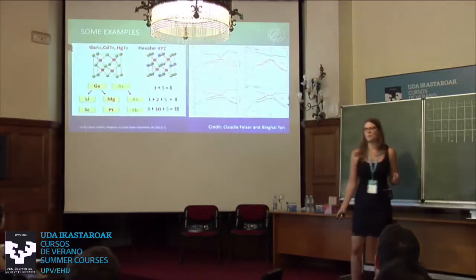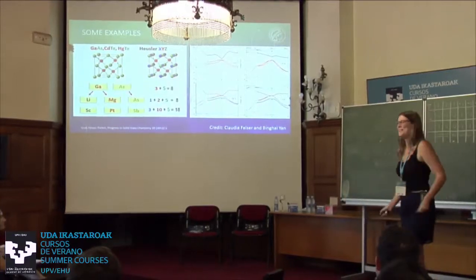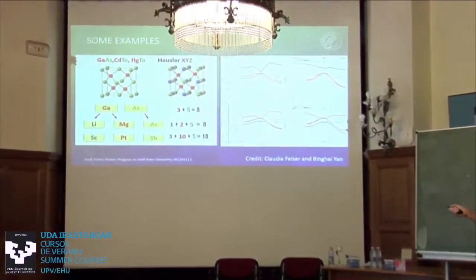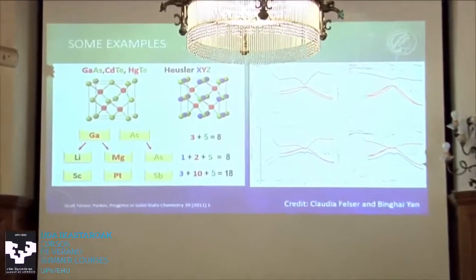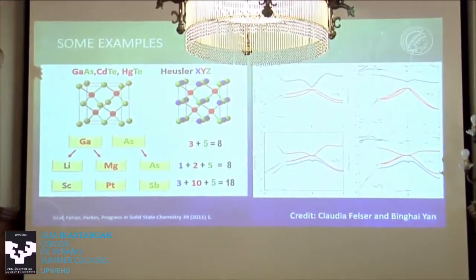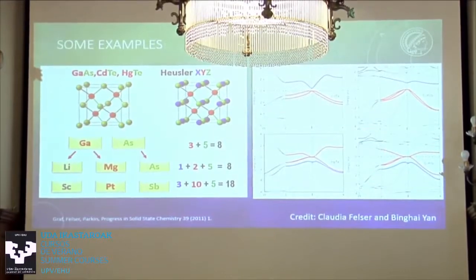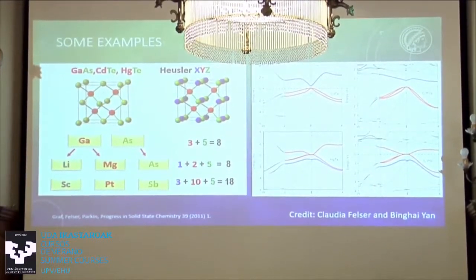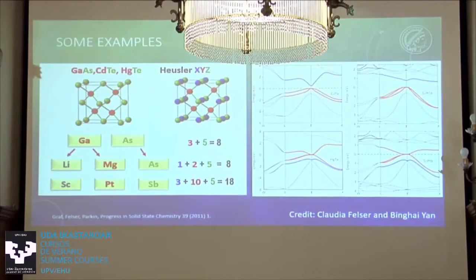This is a slide I stole from Claudia. I hope she's not going to tell you the same thing later. If you have a semiconducting compound, you all might know gallium arsenide, you have 3 and 5 electrons, it's 8, so you have a semiconductor. But you can extend that to more complicated materials, for example one with 1 and 2 electrons, and again have 8, and you're still going to have a semiconductor. Or if you add d electrons, you count to 18, and if you have scandium, platinum, antimony, where you wouldn't intuitively think it's a semiconductor, still, because the counts match, you have a semiconducting compound.